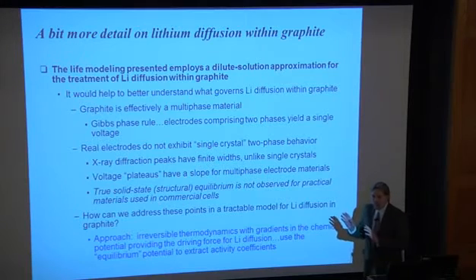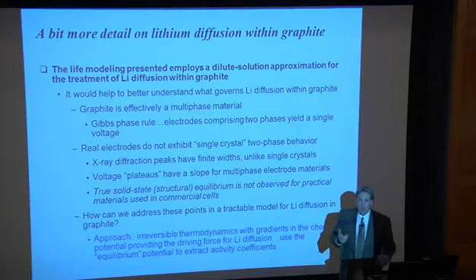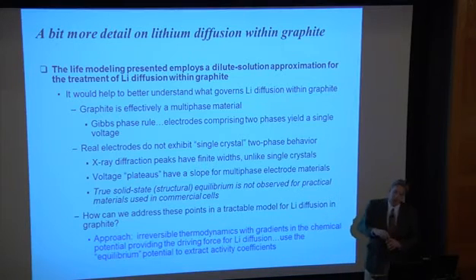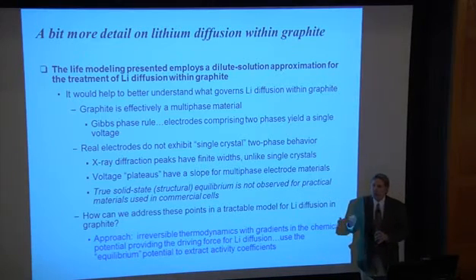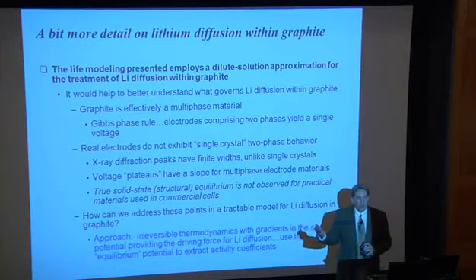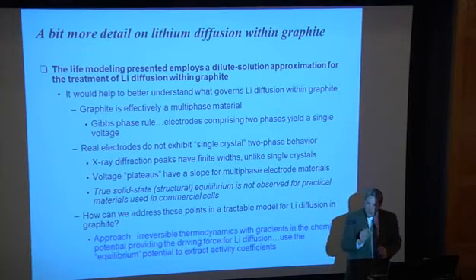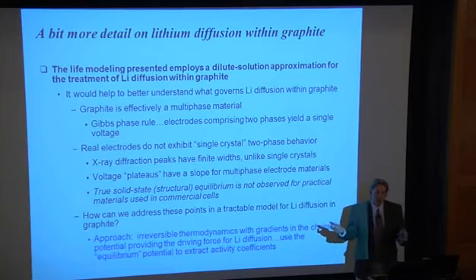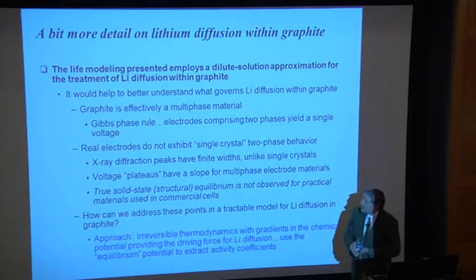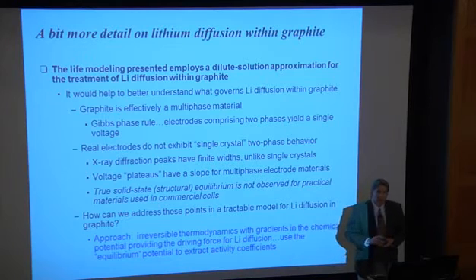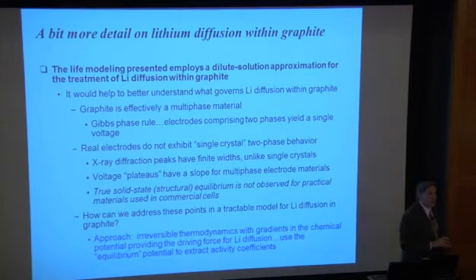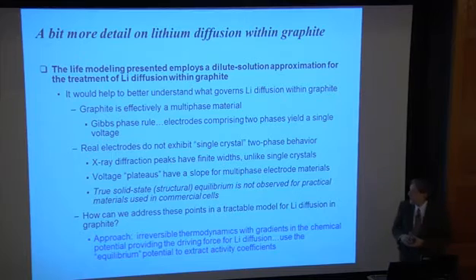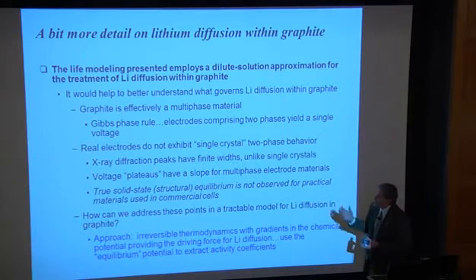Now, that was a really simple model. And I mentioned that you can get some asymptotic expressions because it's very low rate. That helps. When you discharge an electric vehicle battery, you drive at least an hour. But the time constant for lithium to diffuse within these small particles is on the order of 30, 40 seconds. And so that's why we could get these very simple expressions to come out. Turns out that when we looked at lithium diffusion and transport in graphite, it's a lot more complicated. And that's what some of these slides are mentioning.